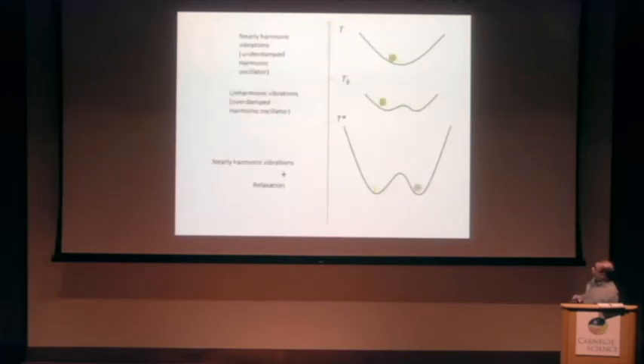circles are experiment. If we think about how to explain our observation with some simple model, we can suggest the following. If this is the potential relief at high temperature above the Burns temperature, we observe only vibrations. And the response can be described by a single underdamped harmonic oscillator. Below the Burns temperature, TB, we observe overdamping, and this could be described as the change of potential relief and harmonic vibrations. And below T-star temperature, we observe the emergence of relaxation. Thus, we have relaxation plus harmonic vibrations due to phonons.